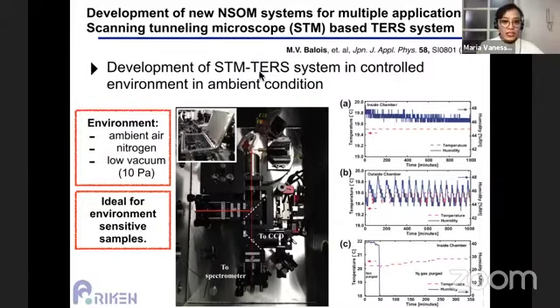Now, for the STM TERS system, we also improved the environment by putting our system inside a metallic environment control chamber, wherein, as you can clearly see here, inside the chamber the temperature is very stable and the humidity does not vary much. The humidity varies only maybe plus minus 1% RH. But outside the chamber, you can see the very dramatic change of the temperature, which is not good for our system.